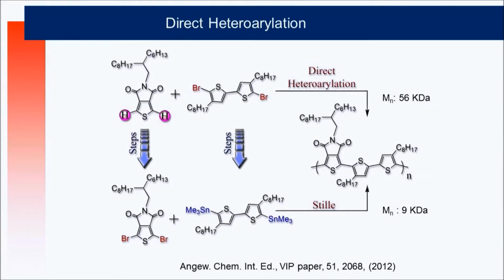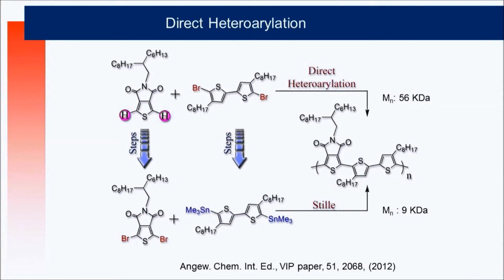So my student came to me and we said, TPD is the perfect monomer for us because you just have two CH bonds exactly where you want. And there is no other CH bond here. And if you take a bithiophene and you make the dibromothiophene instead of the stannylated bithiophene, so this is the typical reaction to make this polymer for thin film transistors, let's say. And that's the reaction my student proposed to me 2-3 years ago. And I didn't believe it. I said it won't work. It will never work. Come back when it works. See you in 1 year.